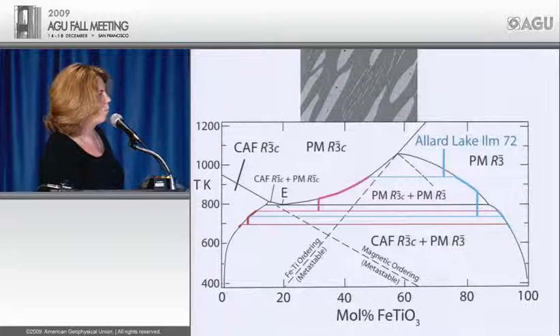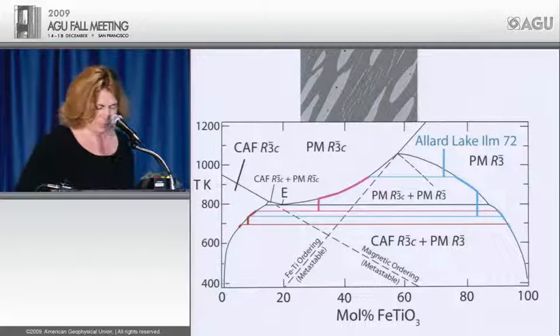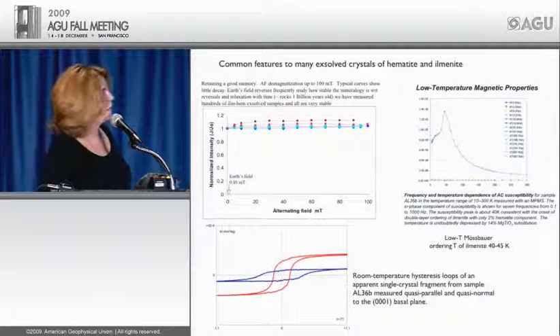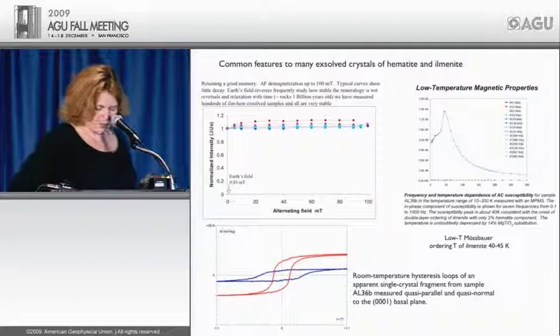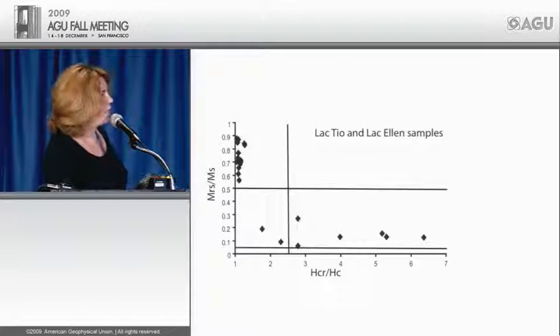It's never end member, but the ilmenite end is more towards end member than the hematite end. Again, the basic magnetic properties: we have extremely high median destructive fields, very little variation in any of the samples with alternating frequency susceptibility going down temperature, and also, as I'd explained earlier, a large range in coercivity values. However, many of the samples, those which do not have magnetite, plot way up.